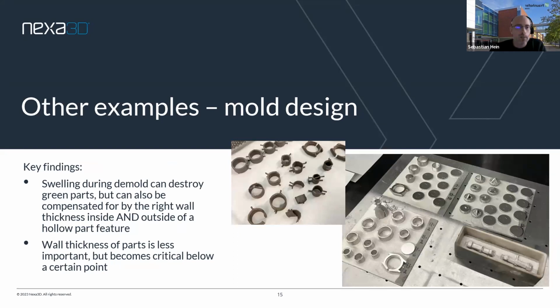So what we try to see is these wall thicknesses that we can make, and you can see sometimes these parts break. So there is some kind of a minimal wall thickness. It's very dependent on the feedstock, and we didn't investigate different feedstocks here, but we saw that you can go, for example, for this cutter mold in this case, down to about 1 millimeter wall thickness, freestanding, so to say. But as you can see on the right side on the photo, where we have sintered parts, there are some parts that have even some issues that you can see with cracks. So it's not that everything that we do always works perfectly.